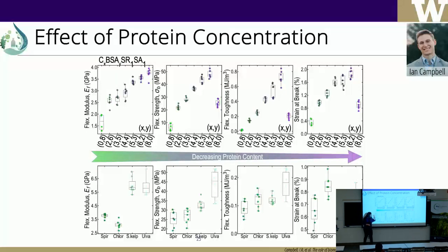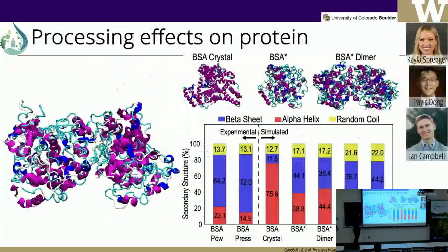Here we're laying down the flexural properties for four different types of biomasses that we're trying to understand, to simulate. And you will see that we laid them down in order of decreasing protein content. So this is the material that has the highest amount of protein, 65%, and then we're going to have lower and lower amounts of protein. You will see that as our protein amount decreases, we do follow a similar pattern, at least in terms of our strength, where we would be expecting to see some similarities, even though that is very, very crude. And if you are critical, you should be saying, okay, it's not just the protein concentration that you're varying here. Of course, here you also have carbohydrates and higher molecular weight and tissue connectivity. And I would tell you, yes, you're absolutely right. But now we are laying them down by protein concentration, and that does make sense.